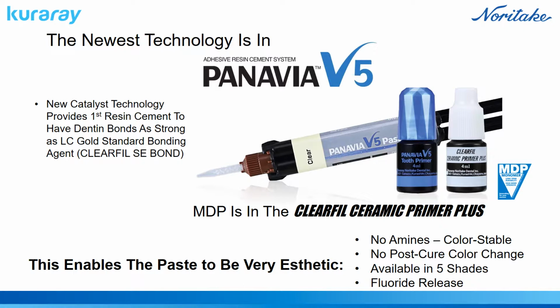So our newest technology is in Panavia V5. Panavia V5 has a new catalyst technology, and this catalyst technology is in this resin cement here and in this tooth primer. When these two come together, they are able to self-cure as strong as if you light cured it, or as strong as if you light cured Clearfil SE Bond, which is a gold standard bonding system that came out in 1999. This is a milestone in adhesion dentistry. Most resin cements, when you let them self-cure, are much weaker than their light cure version. This is no longer true with Panavia V5.